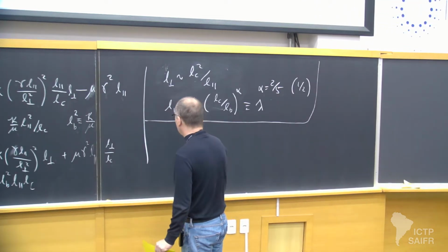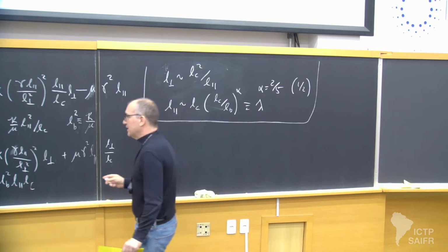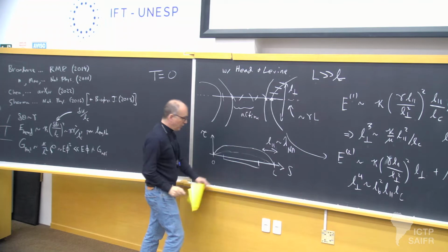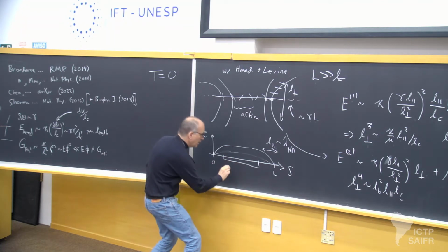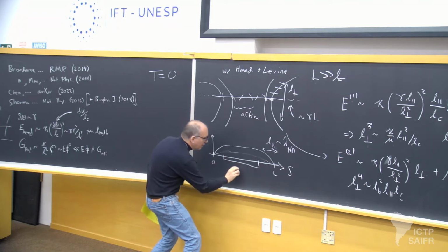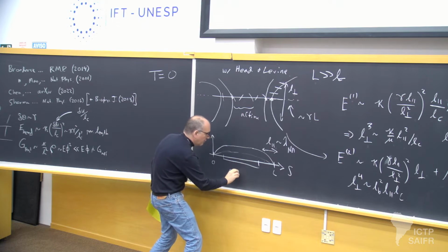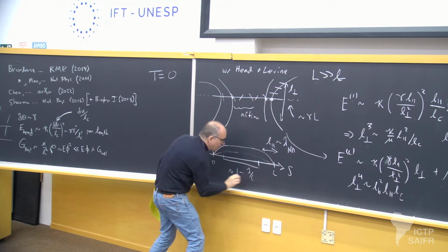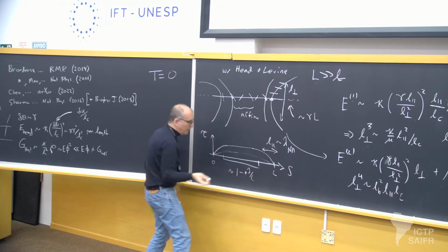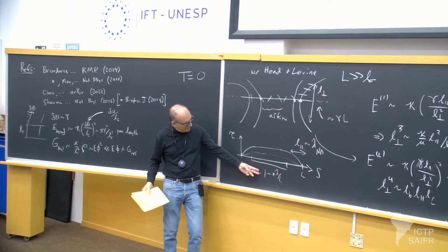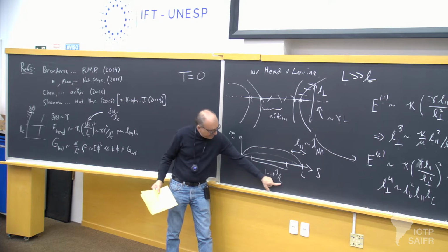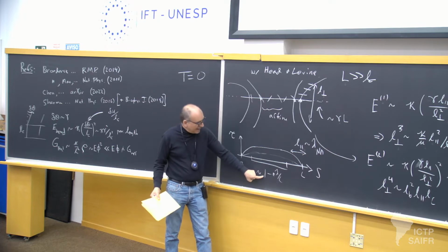So if that's true, then notice what that says. That means that the affinely deforming part of the fiber is a fraction of order 1 minus lambda over L with some coefficient. So in other words, it's basically telling me that in the limit of very high molecular weight, I get almost all of the fibers being stretched.